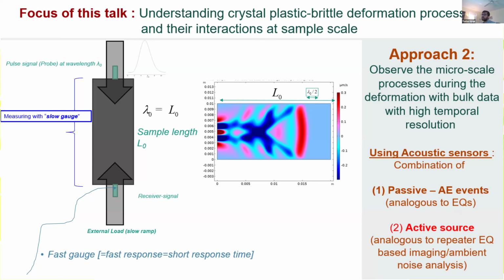So what I'm going to show you today is some work particularly focused on active source. In a lot of the experiments that I'm going to show you results from, we have both AE events, the passive source, as well as active source. But just in the interest of time, I'm going to focus on the active source analysis and trying to see what information we can get. A lot of people do this type of analysis already, but just to make sure everybody's on the same page, the basic setup is that we have a sample, it's being deformed, and we have two sensors. We have a sensor at the top of the sample, and a sensor at the bottom. At a given point in time, you send a pulse from the top, and then you listen at the base. In some way, it's a way to probe what's happening as the sample is deforming. It's the same idea as a pump and probe type analysis.